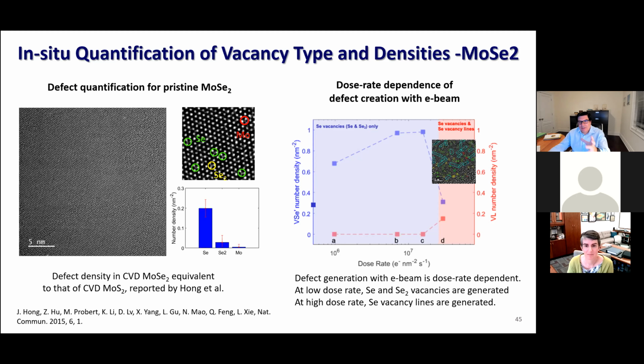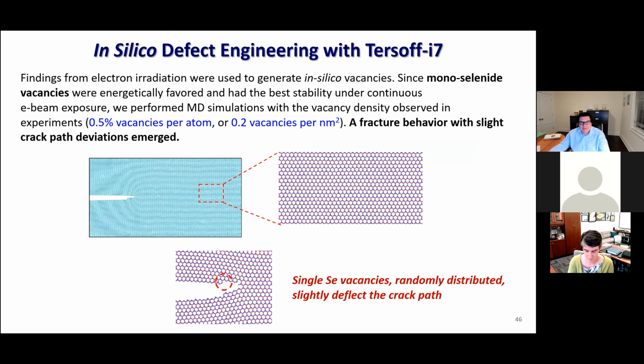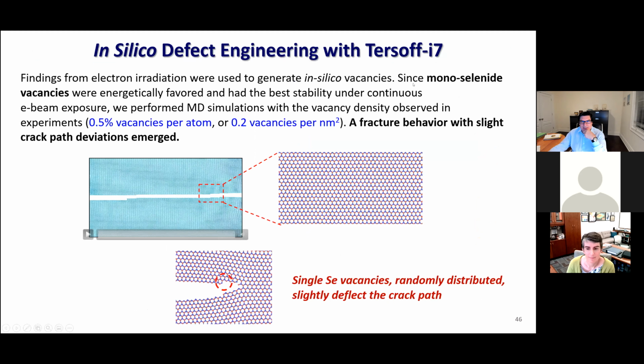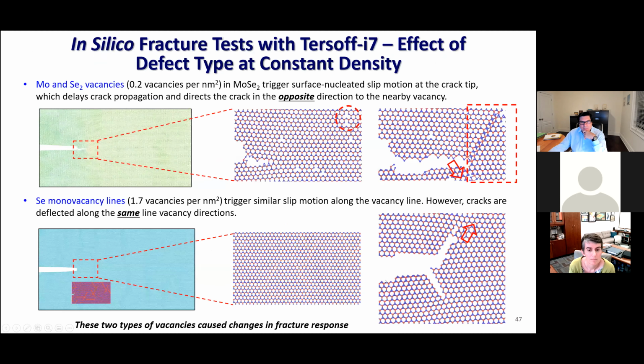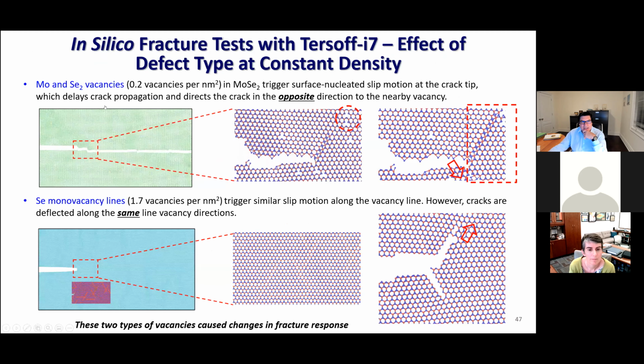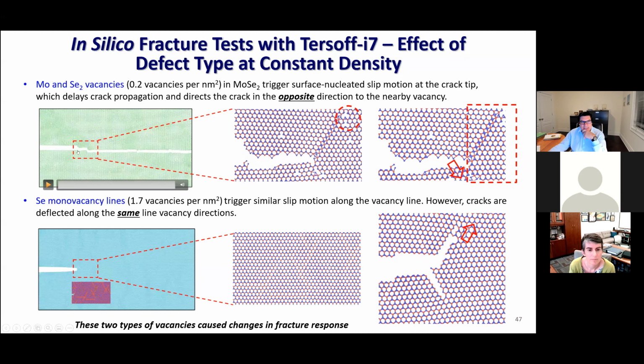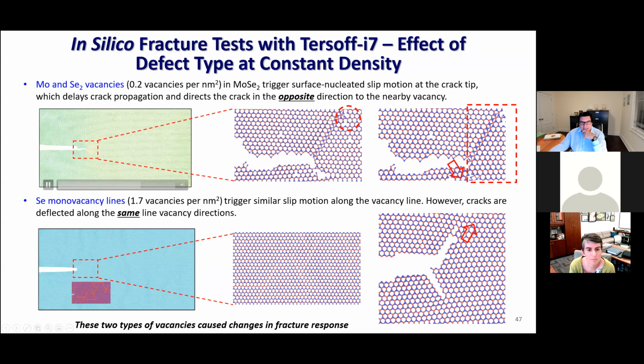So this is just to say that we use densities that are experimentally sound. But then we went in silico and we look at random single vacancies, monoselenide vacancies, and we observe that, yeah, the crack propagates and can deflect, but there is no major toughening associated with it. More interestingly, when we have other vacancy clusters, you see here, there is an arrest of the crack, shearing, and then propagation again.